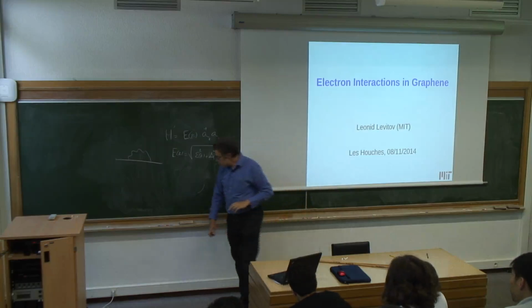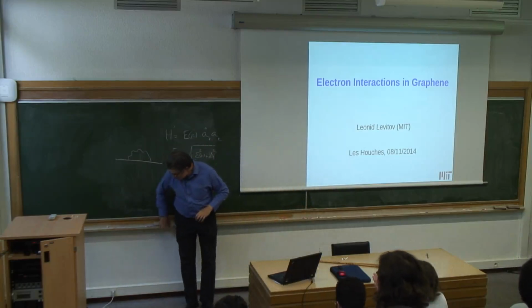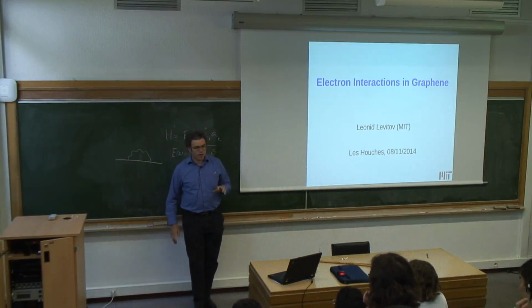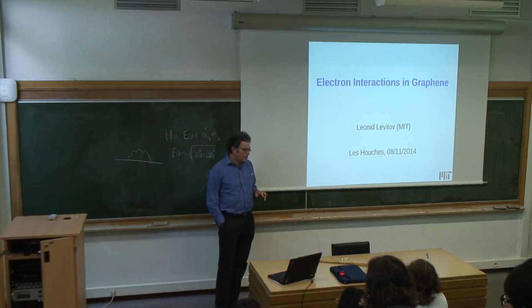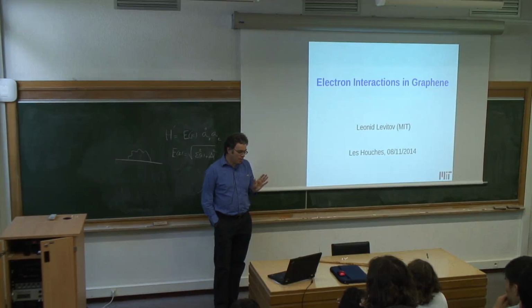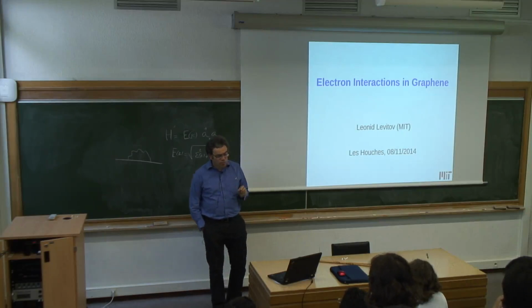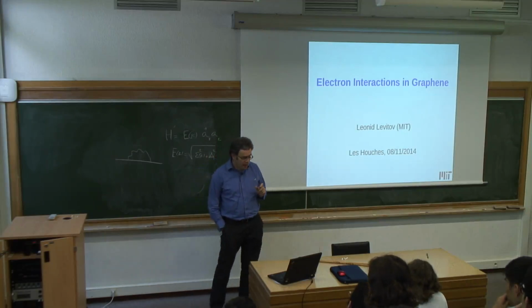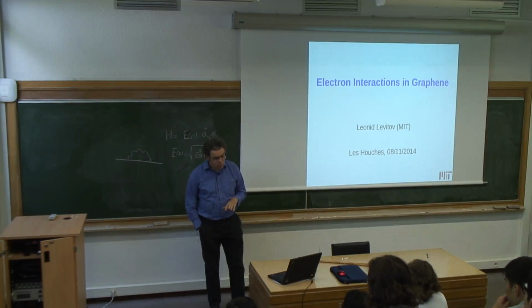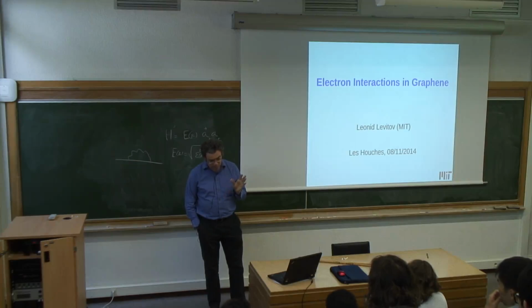Yeah. So okay. So let's start with graphite. Graphite doesn't have intrinsic superconductivity, or maybe it does, but it's too small because electron-phonon coupling somehow is too weak. The reason is probably that graphite is non-polar, right? However, graphite can be made superconducting if you dope it. There is chemically intercalated graphite. If you intercalate it with alkalis, you can get temperatures as high as 10, 12 Kelvin, right?